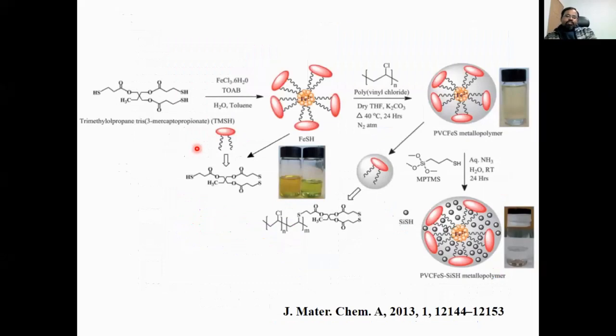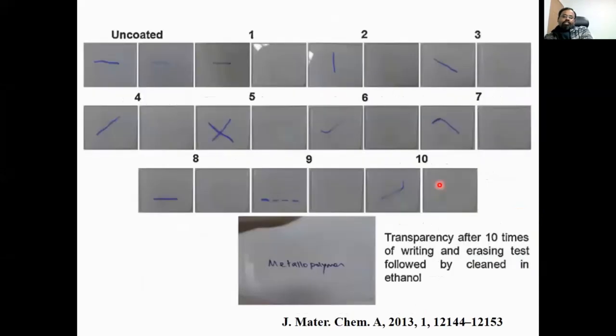Further, we are interested in developing highly hydrophobic coatings using PVC and mercaptan-based metallopolymers. We used iron here. We used an iron source as a precursor to make cross-linking with these mercaptan precursors. And we developed these coating materials to be highly transparent and also very stable. It shows very good hydrophobicity as well as transparency, and the stability is also very good. Its hardness is almost 7 to 8 H, meaning this coating on the glass substrate is completely stable.